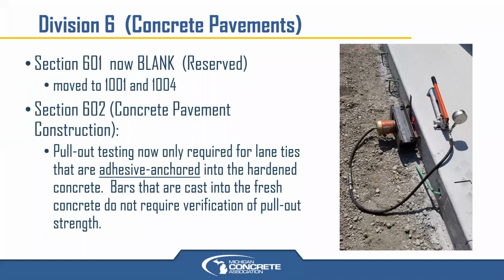Section 602, concrete pavement construction. You see a shot here of lane ties doing the destructive testing, lane tie pullout resistance, where they jack to see the pullout resistance of that lane tie in the concrete slab. That exact one that you see, I'm not sure if those were implanted or are epoxy coated. It's hard to tell from the photo. But if those were implanted in the fresh concrete, whether slip form or fixed form through the forms, that would not be required now for the future.